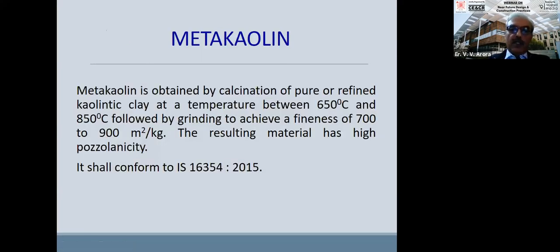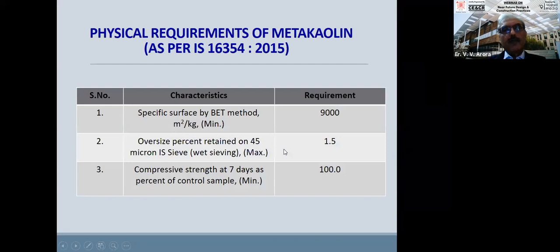The metakaolin document had come in 2015. The fineness of metakaolin is 700 to 900 meter square per kg. It's a very fine material, ultrafine material. It has very high pozzolanicity. But we are not making much metakaolin in India, because of the clay limitation. Kaolinitic clay is required for this. However, we do have some kaolinitic clay reserves also. So we will see some usage of this in the near future.